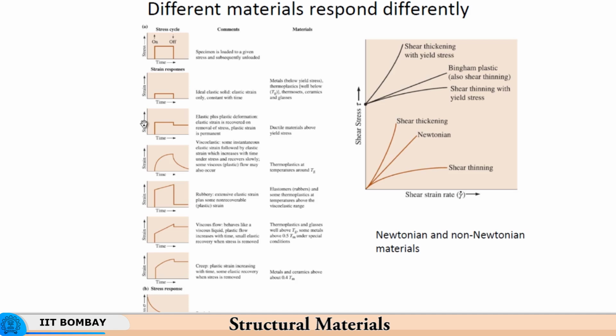viscoelastic response, because now when we say viscous fluid, it means that it hardens with strain rate. So, the very definition of viscous material is that it hardens or increases in strength with respect to strain rate. So, here there is an increase in the strength of the material with strain rate, and as a result, for a given stress, the load required to deform continuously increases, and the strain rate therefore falls. It keeps falling up to a point, and then when the load is removed, again the material does not come back; the strain is not recovered immediately.